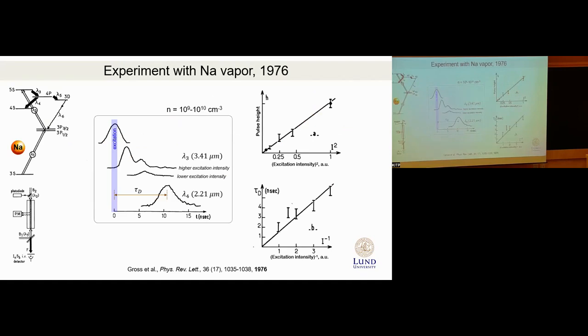The next experiment was in sodium vapor, 1976, by the group of Serge Haroche, who got the Nobel Prize recently. In this case, they again had an elongated cell, a gas of sodium atoms, pumped it with two pulses to the 5s state, and then observed again a delayed emission of light, which varied with the excitation intensity. Higher excitation intensity gave faster superfluorescence, lower excitation intensity gave slower superfluorescence. They did it for two transitions, plotting the decay time versus excitation intensity. Here it's inverse. And then again, intensity versus excitation intensity squared, a linear trend as one would expect for the Dicke case.